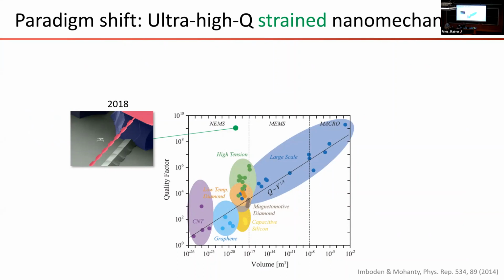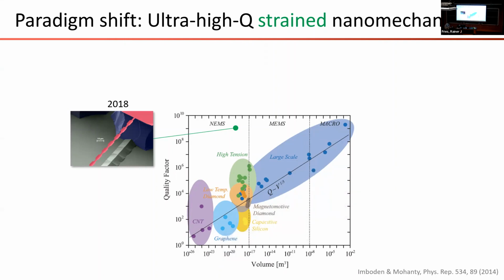So here you're looking at a plot of the quality factor versus mode volume of many different types of solid state mechanical resonators over the last 20 years or so, compiled by Imboden and Mohanty in 2014. You can see that the Q scales roughly as the cube root of the volume, independent of loss mechanism and independent of geometry of the mechanical oscillator, varying from carbon nanotubes to silicon cantilevers in atomic force microscopes to MEMS oscillators to gravitational wave test masses. The reason for that, roughly, is that loss typically gets worse for small objects as the surface to volume ratio increases. So this green region here is an anomaly.